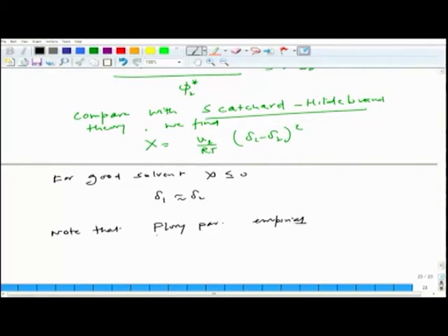If you try to find out this chi from polymer concentration and polymer size dependence, or based on neutron scattering and from calorimetry, it will be found to be different. So, usually these are not consistent, and chi essentially is dependent on the polymer concentration and is also polymer size dependent.